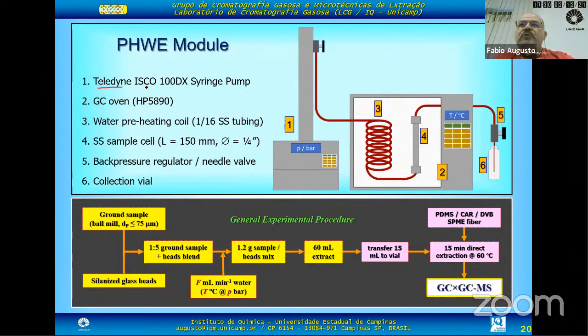We use a very old LC syringe pump to impulse the water through the system. We use a very old GC oven to keep the temperature of the system. This is a GC oven that was stored to be discarded, which we took to use for heating. There's a heating coil inside. The sample cell is a stainless steel tube, with two nuts to keep the sample inside. Here is a back pressure regulator, and the flask to collect your sample.